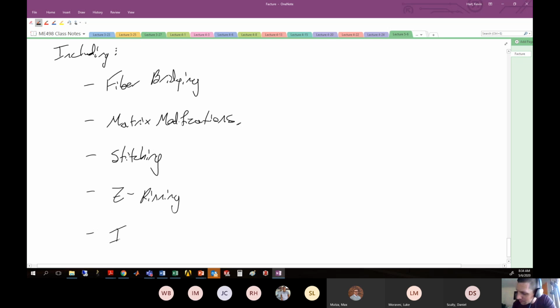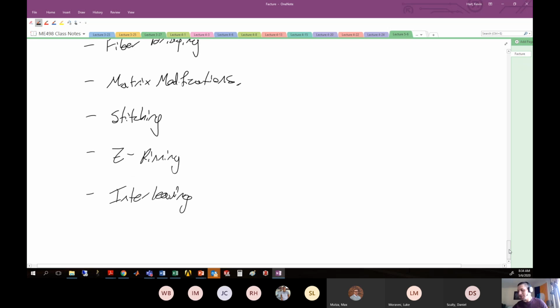There's an idea called interleaving. This one is interesting, and it's the inclusion of very thin thermoplastic layers between the composite laminate layers. So if you can incorporate, let's say, a thermoplastic urethane between individual layers of the laminate, then you would really toughen up the interface between the two different layers. So that's an interesting idea, except there's a drawback there because it really decreases the overarching mechanical properties of the piece, and also architectural modifications.